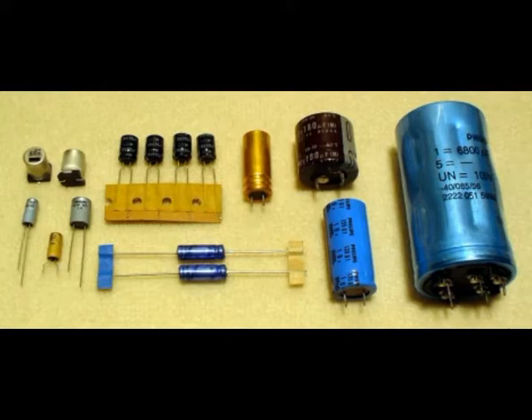After etching the aluminum anode, the roughened surface is anodically oxidized, or formed. An electrically insulating oxide layer, aluminium oxide, is thereby formed on the aluminum surface by application of a current in correct polarity if it is inserted in an electrolytic bath. This oxide layer is the capacitor dielectric. This process of oxide formation is carried out in two reaction steps whereby the oxygen for this reaction has to come from the electrolyte. First, a strongly exothermic reaction transforms the metallic aluminum, Al, into aluminium hydroxide.